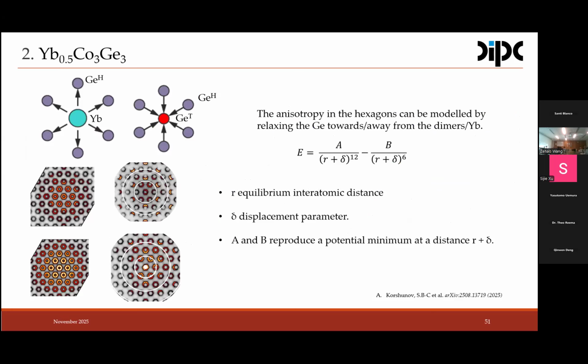But anyway, what really matters is that we can model the diffuse scattering with the anisotropic hexagonal shape, considering all the atoms in the unit cell. In this case, we do not only have these germanium pairs in the Hamiltonian, but also consider out-of-plane and in-plane displacement of ytterbium atoms towards the hexagonal honeycomb germanium, and the honeycomb germanium towards the trigonal germanium. If you consider all of this, we model this with the Hamiltonian, including this Lennard-Jones potential, we can come up with a perfect description of the diffuse scattering. The paper is accepted and will likely be published this week. So if you want to look at it.